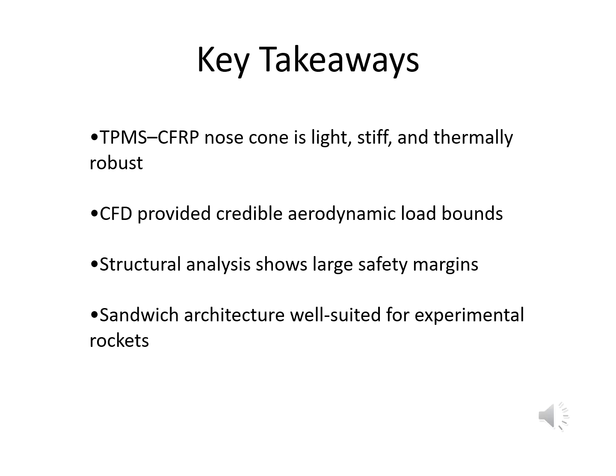In summary, we developed and demonstrated an ANSYS-based workflow that integrates CFD, TPMS homogenization, structural analysis, and in the near future, thermal evaluation. The TPMS core provided excellent stiffness to mass performance, while the carbon fiber skin carried the major loading with very high safety margin. The sandwich structure showed minimal deformation under aerodynamic conditions.